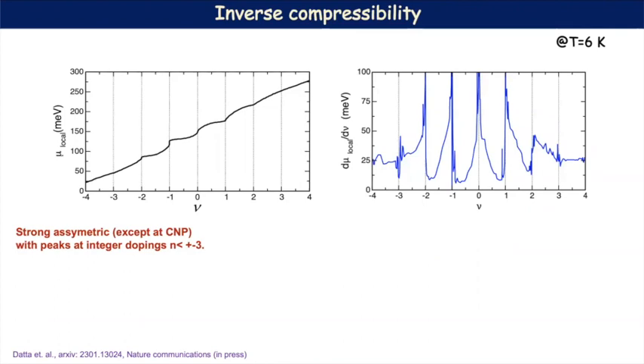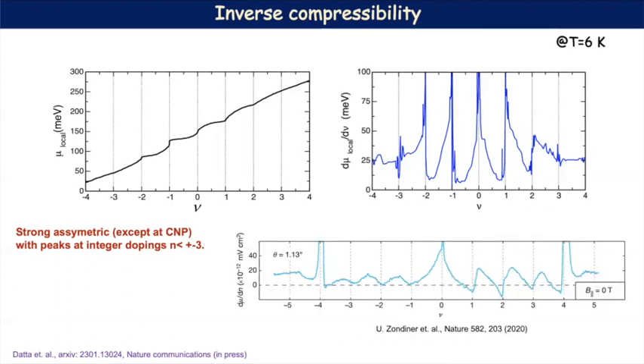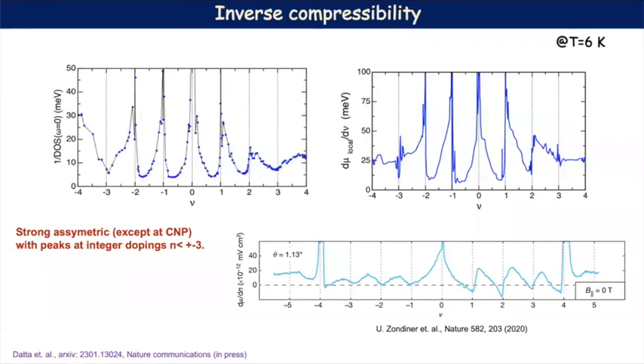Now I want to remind you about this experimental picture where they find this profile of inverse compressibility. You can see this sawtooth-like profile with doping looks very similar to what we have obtained from our calculations. And here, these asymmetric peaks are described as a result of symmetry breaking due to ferromagnetic polarization. But in our case, we don't have any symmetry breaking in the system. So in this case, we can explain it in terms of the spectral weight reorganization due to correlations again. If I show you this inverse of density of states at omega equal to 0, you can see this profile, which is almost exactly the same as the inverse compressibility.